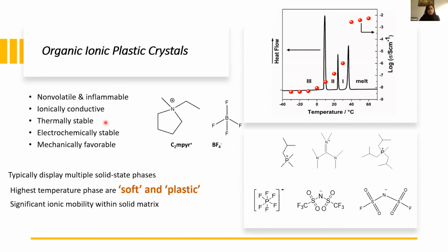One type of these electrolytes is organic ionic plastic crystals, which are a solid state family of ionic liquids that Christina talked about yesterday. These materials are solid, but they are mechanically flexible solids because they go through some solid-solid phase transitions at the solid state, and so they have a disordered structure. And finally, at the highest temperature solid phase, just before melt, they are soft and plastic.